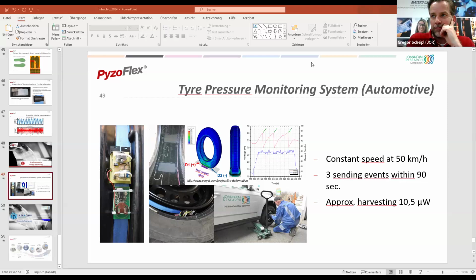I would say, due to the fact that we do printing, screen printing, sheet to sheet, the answer is printing. We tried, of course, currently we're working in the field of inkjet, but we also tried gravure printing in the field of roll-to-roll, spray coating, dip coating, and whatsoever. As a prerequisite for the sensor having good functionality is a homogeneous and dense PVDF-TrFE layer. We found out that currently printing is the process to use.